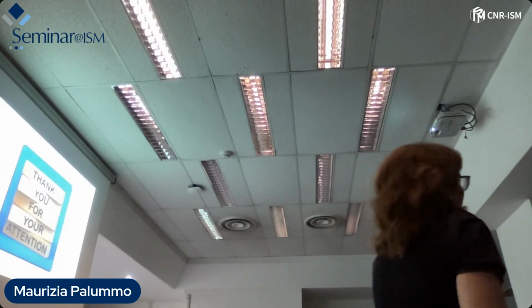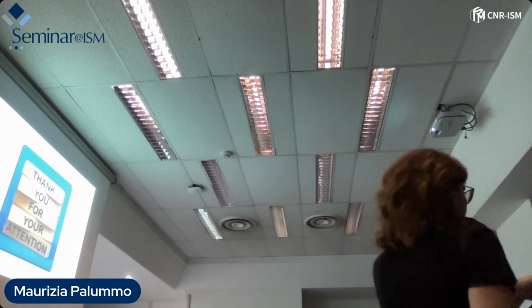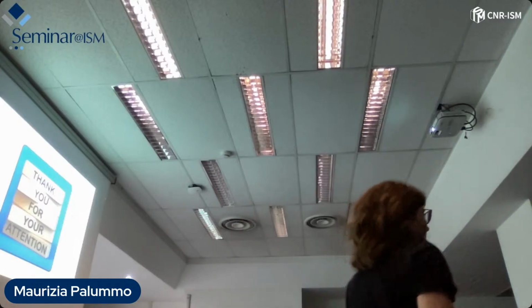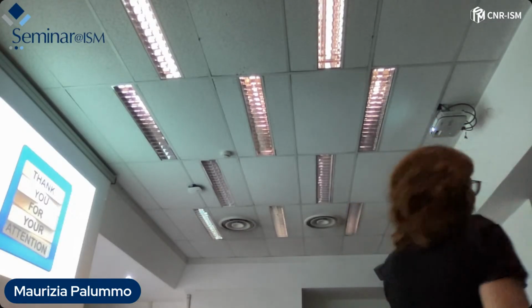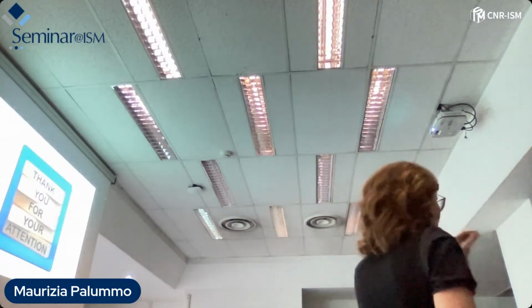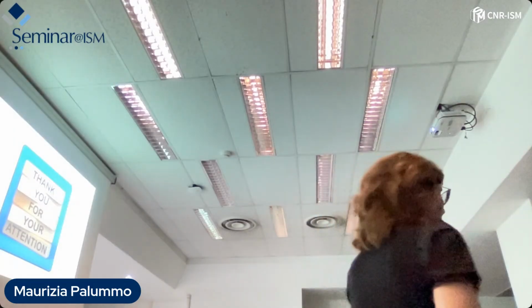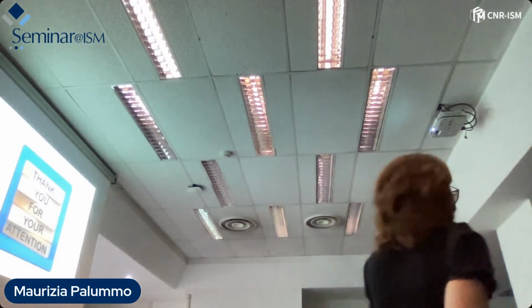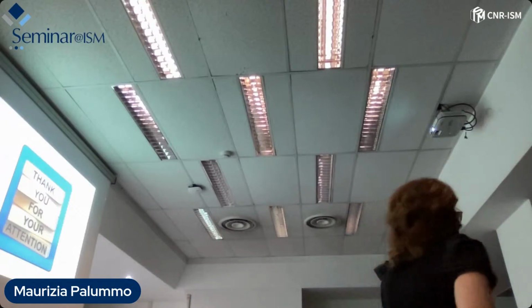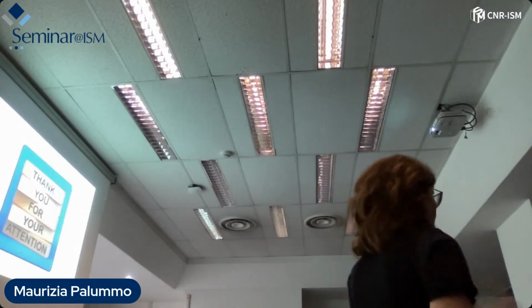Stefano. In the case of perovskite, no, because the simulations, I didn't mention all the technicalities, are not at all obvious. For instance, in the first case, we calculated the structure, completely took out the organic part, and put cesium to saturate, which was needed in the calculation. We realized that the band structure near the region we are interested in was okay, and we did the calculation with cesium because the number of atoms was too big. In this last simulation, I shifted everything by 0.2, 0.3 V because the agreement is not good, due to computational problems.